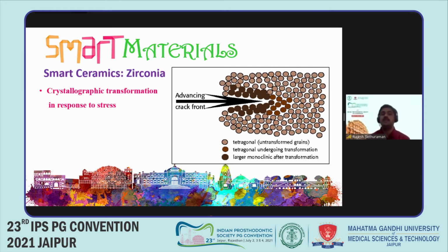Why is it that this particular material needs to be used? It is because when I have a stress, whether it is because I am reducing it, I'm polishing it, or adjusting the occlusion inside the mouth, or the zirconia is being subjected to load, the surface flaws or the Griffith flaws which exist on the surface have a tendency to propagate inside zirconia. Now, zirconia, being crystallographic in structure, has a tendency to allow the crack to propagate. And if a crack propagates and reaches the base, you have a very visible fracture and failure of the restoration.